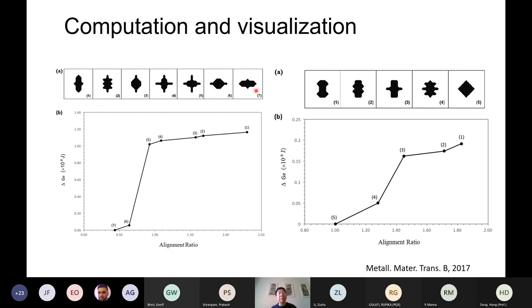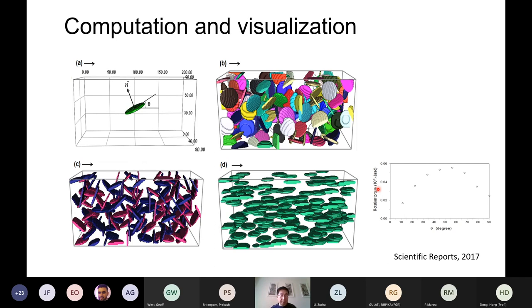So from 1 to 7 are different morphologies of the inclusion, and the free energy corresponds to each in a different way. That means if you have a current from left to right, this inclusion will grow in a pattern which is parallel to the electric field. This is another case with the same volume but a different shape, so which will be preferred? This shape will be more preferred than this one, according to the free energy. So this is another case to predict.